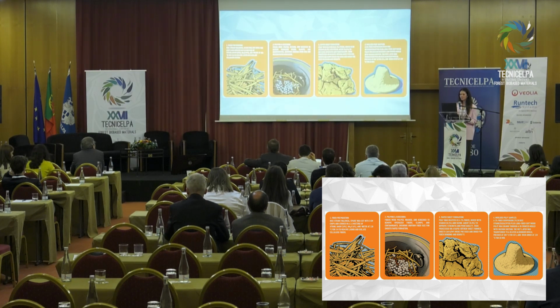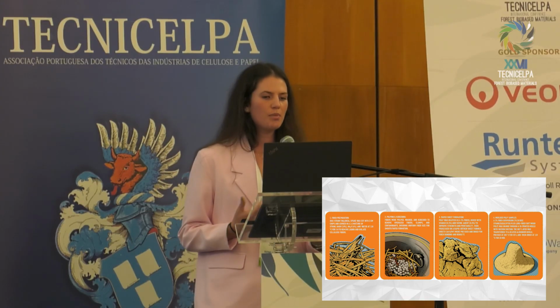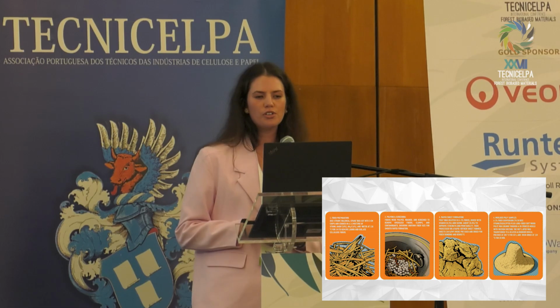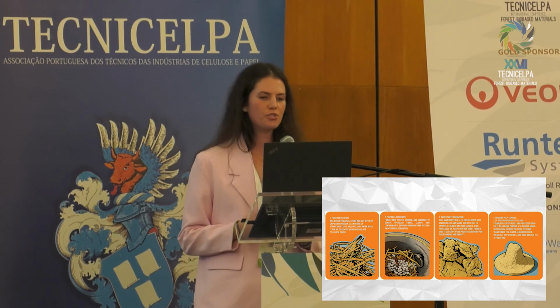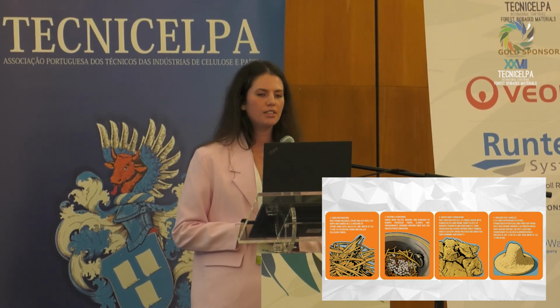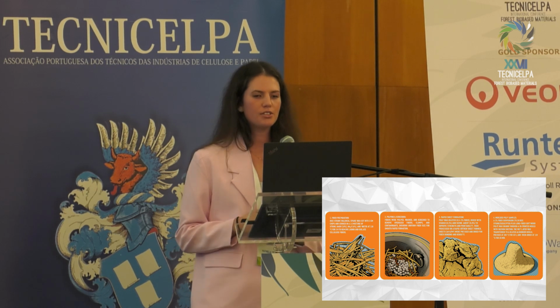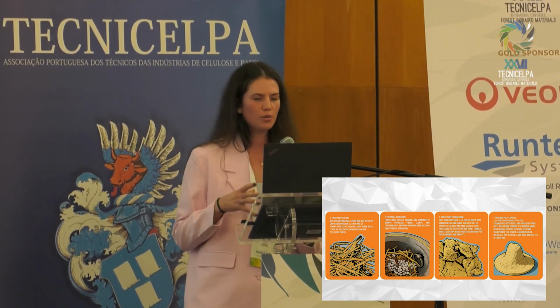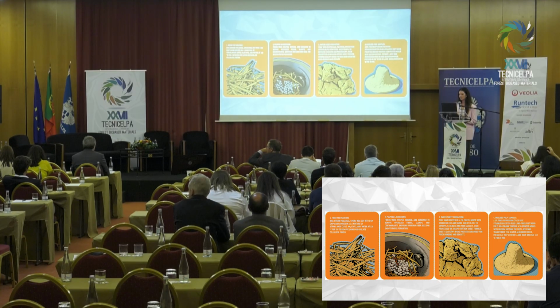So what did we do? First, the rice straw from Spain was cut into 3 centimeter chips and then cooked in water for 3 hours at 110 degrees. Fibers were then pulped, washed, and screened to remove oversized clumps. And then the pulp was diluted, mixed with starch and sizing agent to improve strength and printability, and then processed on a sheet former. A 1% fiber suspension with 70% of rice straw and 30% of long fibers was then drawn through a 3D printed mold with vacuum suction, and the wet layer was then transferred to a heated aluminum mold. We did the same with only eucalyptus fibers and long fibers to then see the results.